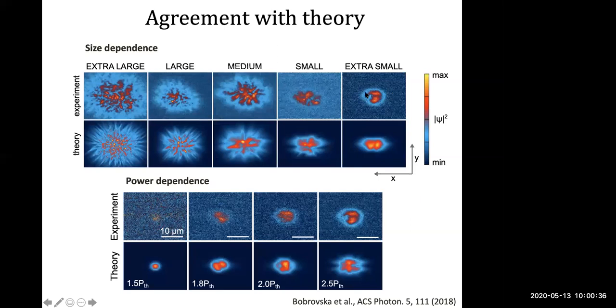If you look at experiments comparing the condensate images as a function of pump spot to theory calculations, you see that the agreement is quite good. These instabilities clearly cause a breaking up of the condensate at high power. This is for large pump spots, and the same thing is true as you increase the power of the pump laser. So this is nice work showing that dynamic instabilities are important to consider in these organic polariton condensates when you are working with an open system.